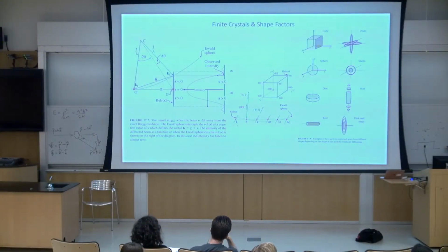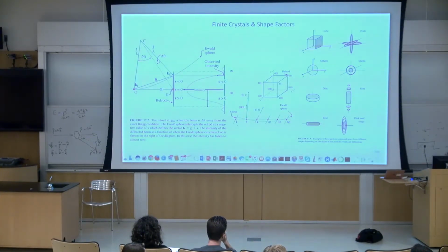The Fourier transform of my shape is very wide, so what I get is something quite narrow, but it's one of these little sinc function-y things, right? And I have to convolve them, so every one of those dots became a little wiggly object. Like that.